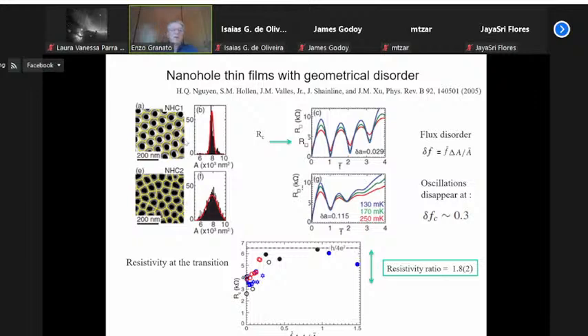They compared the two systems, and they were particularly interested in what happened to the superconductor-insulator transition, and in particular what happened to the resistivity at the transition. How universal is this transition? Or if it's not universal, how does it depend on disorder? This is shown here in the figure on the right. The figure on the top is for small disorder, the sample on the left. The next figure is for large disorder.